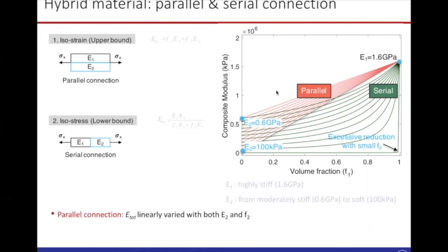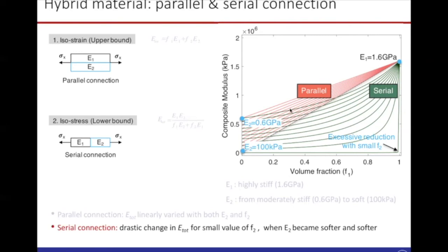Now, in a parallel connection, you can see there's a linear relationship, as you can see in this equation. So E total varies linearly with E2 and F2, meaning that the stiffness will always be high until this F1 approaches very close to 0. But with series connection, the picture is a little bit different. The stiffness of this hybrid material could reduce drastically as E2 becomes softer and softer. When E2 equals 100 kilopascal, as you can see here, there's a large reduction in the stiffness of the hybrid material, even for a small value of F2. Meaning that if you connect a highly stiff material E1 with a very soft material E2, this hybrid material becomes soft and stretchable. So this gives some idea to develop a stiffness tunable hybrid fiber. So how does it work?